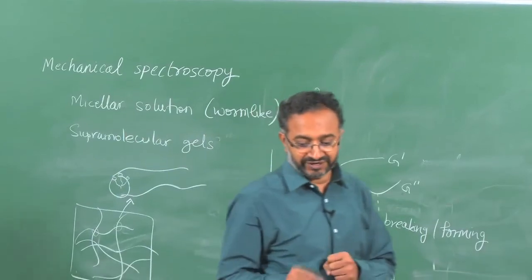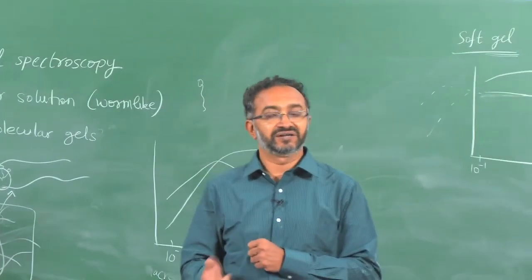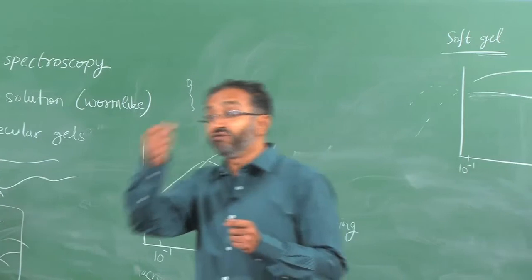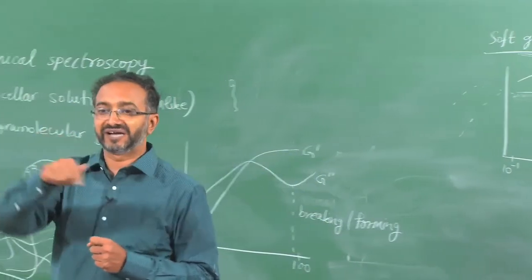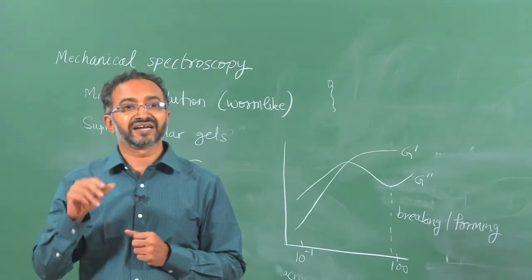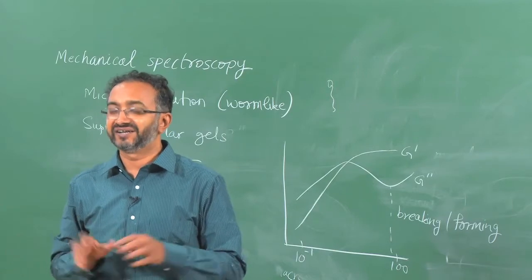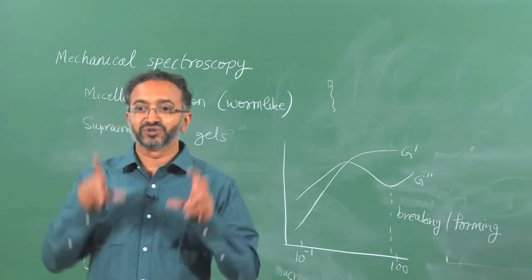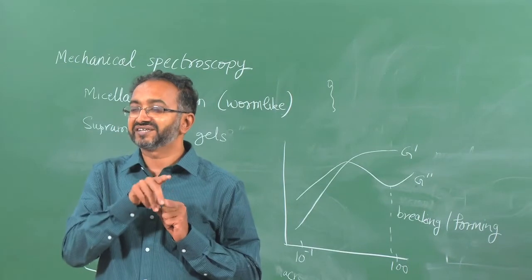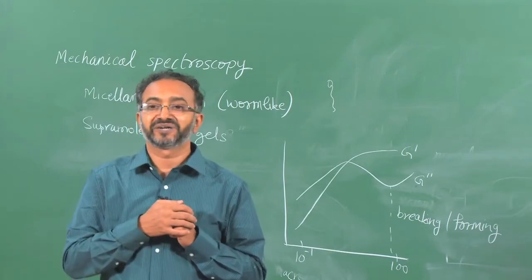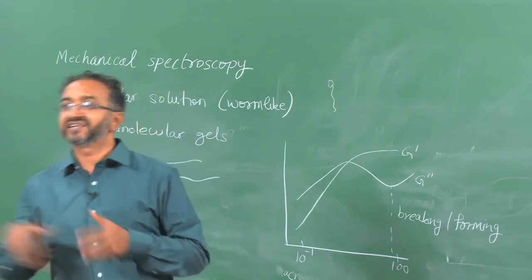For example, one clever experiment which was done was that if the overall molecule response is related to dielectric, while the segmental relaxation is not related to dielectric, then if I do both together, I can show that, oh look, under these time scales I can see the overall reptation motion, while in the other case I do not see it.